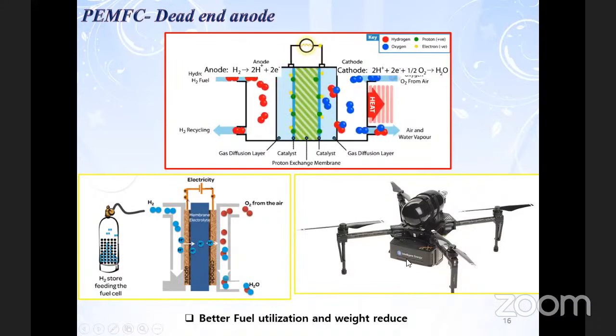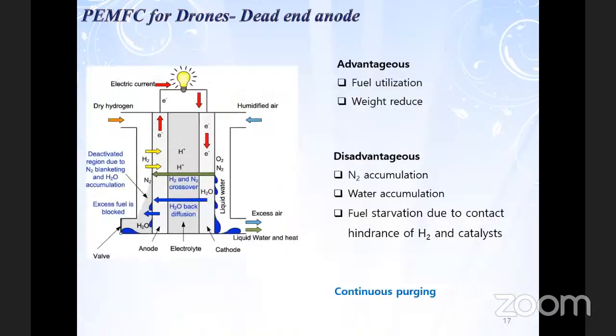And this is the example of the drone I am showing from Intelligent Energy, a very famous and well-established system they have developed. The hydrogen tank is fitted, and down here you see the black color is the fuel cell stack. This fuel cell stack is fitted here, and the hydrogen is provided here. And from the back side, there are fans that can intake the oxygen from the air. Okay, so we block it at one end, and there are advantages like fuel utilization. You are using the fuel as much as possible, so you decrease the weight. If you decrease the weight, you can use maximum payload. But there are disadvantages.